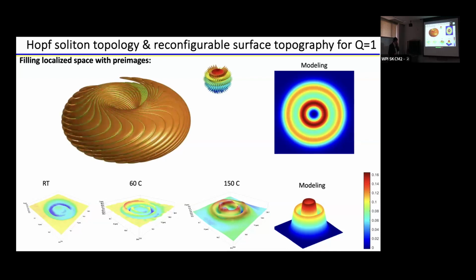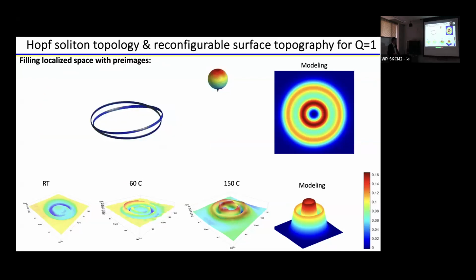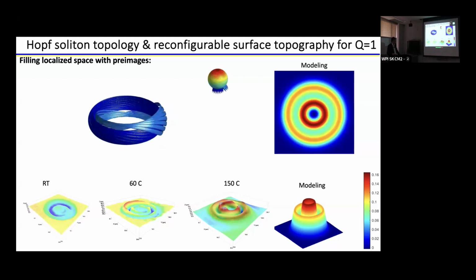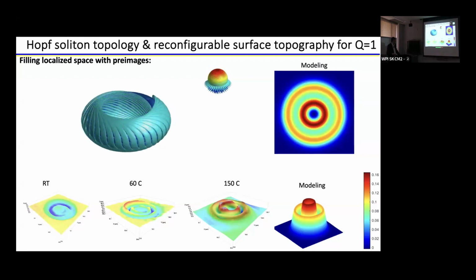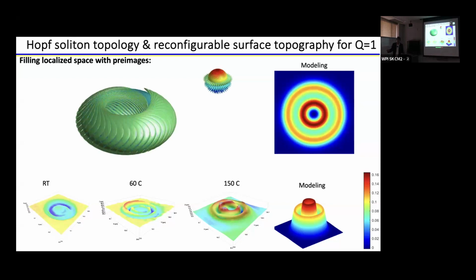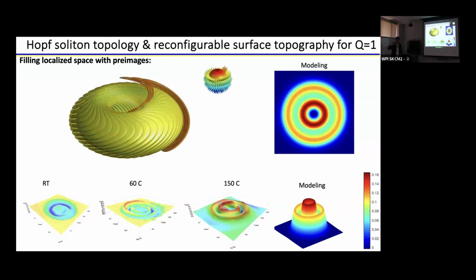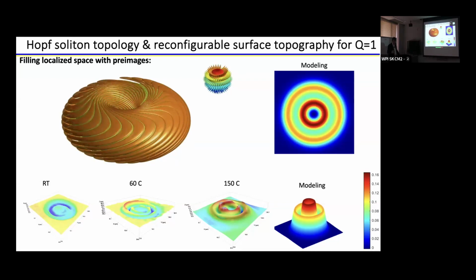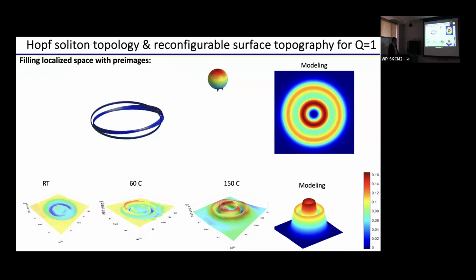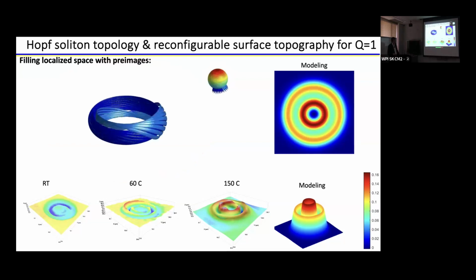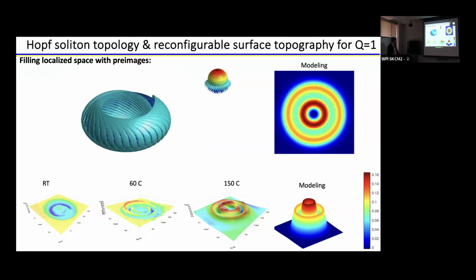So again, in here you can see the surface actuation of such topological objects, and this behavior is reproduced in our modeling. You can see that in this case, the peculiar nature is that, in some way, to me, it was reminding some of these fountains that you sometimes see in downtowns of cities, right, where the water can form such peculiar shapes that can then be controlled in how exactly they evolve. And this is something we do experimentally and see in numerics, where with change in temperature, we can go from these double circular valleys to double circular mountains as temperature is controlled.